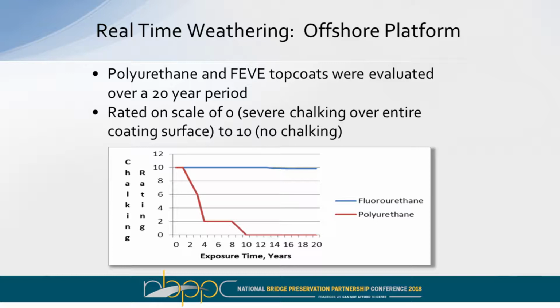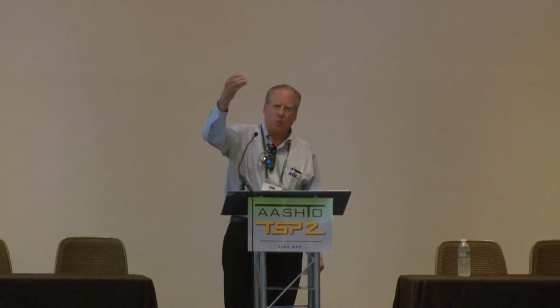10 is considered to be good. If you're down at 0, the panel is completely chalked. And you can see how rapidly the polyurethane, the red line, does start to go down. After about 4 years, you're already getting a lot of chalking on the coating. And all chalking is the polymer degrading and breaking into small bits that can then be washed away with wind and rain, and that's how coatings degrade. If you walk up to your house after 5 or 6 years, you can wipe your fingers on it and you'll see paint on your hands. It's the same thing happening here.